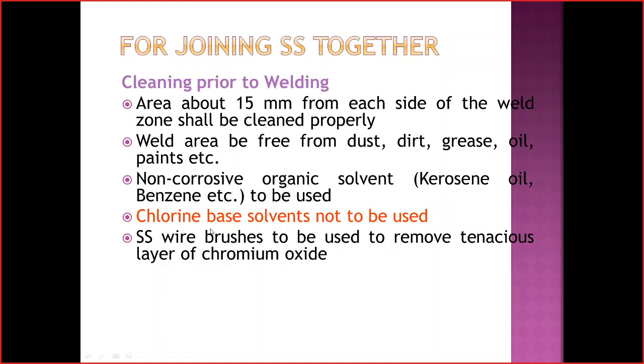But remember that chlorine based solvents must not be used, okay, because it will react with the chromium and the chromium layer will come out and the surface will become rough and it will attract the corrosion again further. So whole work will be wasted. So chlorine based should not be used, only non corrosive organic solvent can be used.